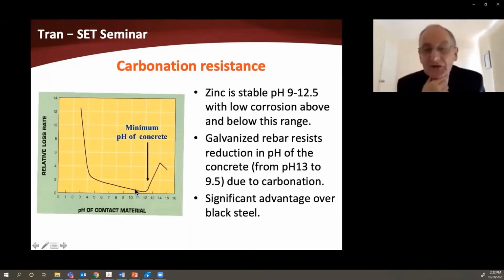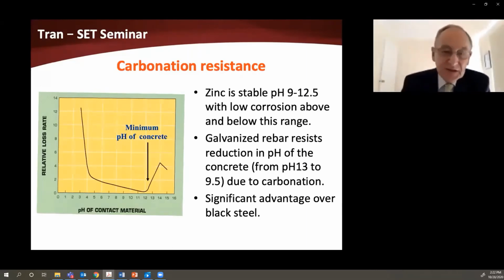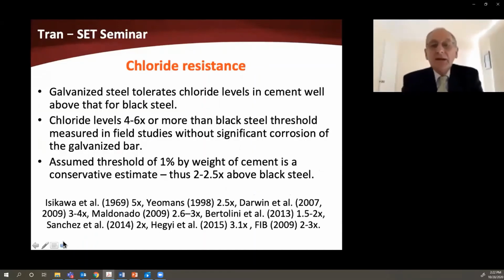Now, carbonation is not a common problem, but it is one of those things that can occur in very thin elements like precast elements and in high water cement ratio concretes and also in poorly compacted concretes. In good quality concrete, it should not be a problem. But the fact is that the zinc can resist this effect, so it's one of the advantages that it has over black steel. Now, the other more important issue, though, is the chloride resistance of galvanizing.